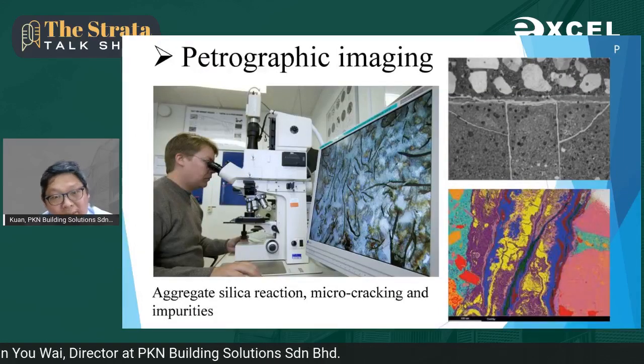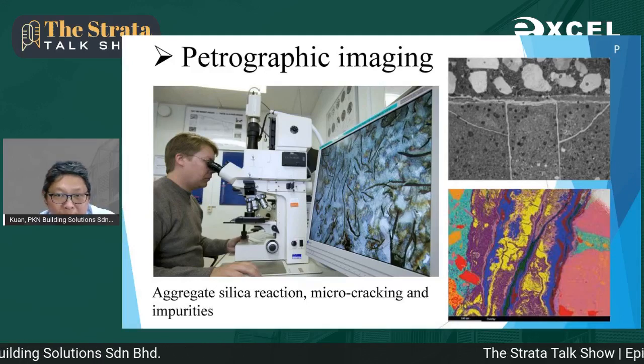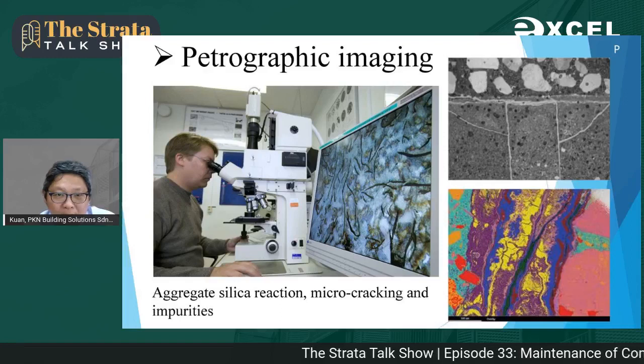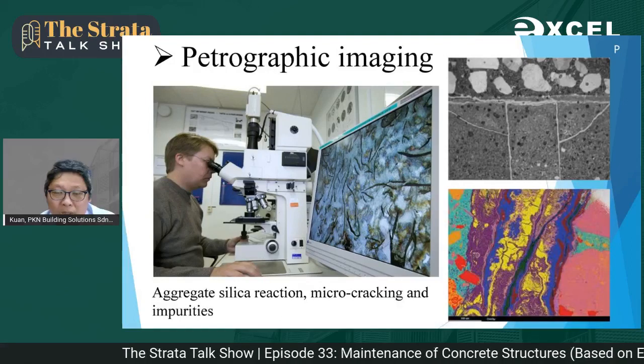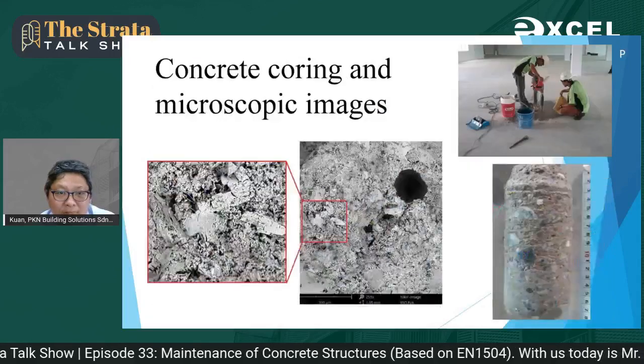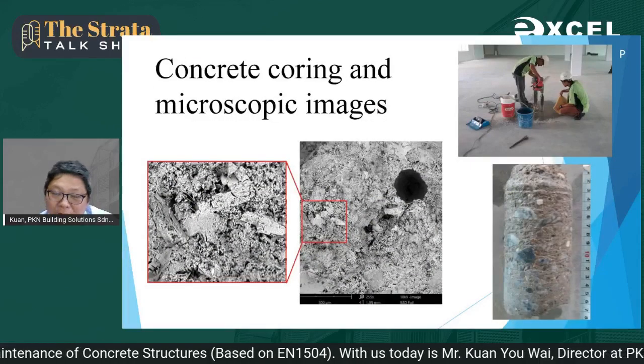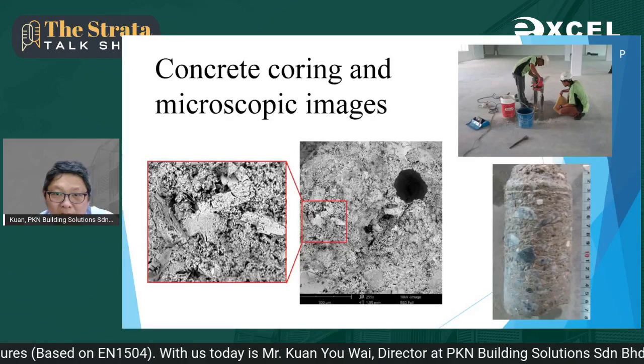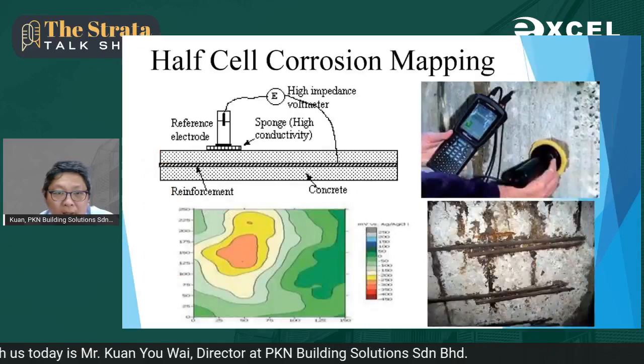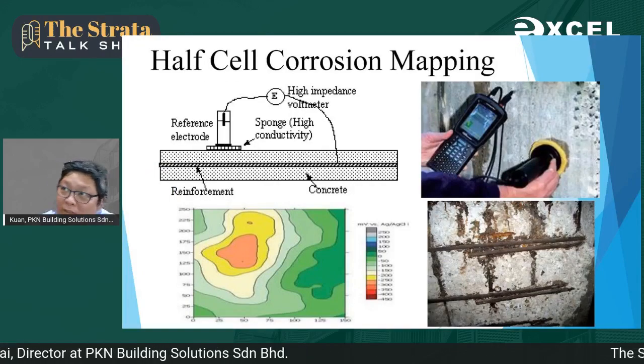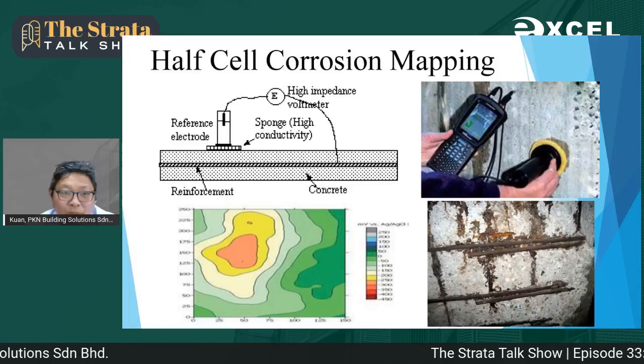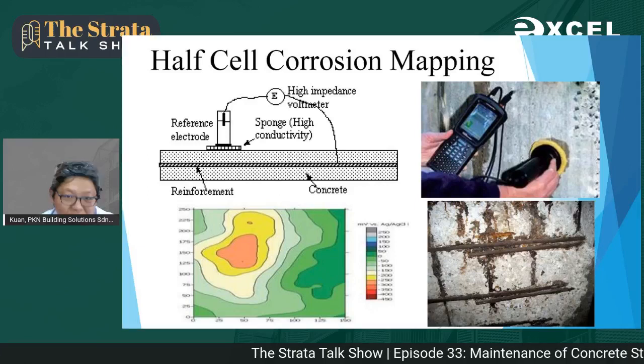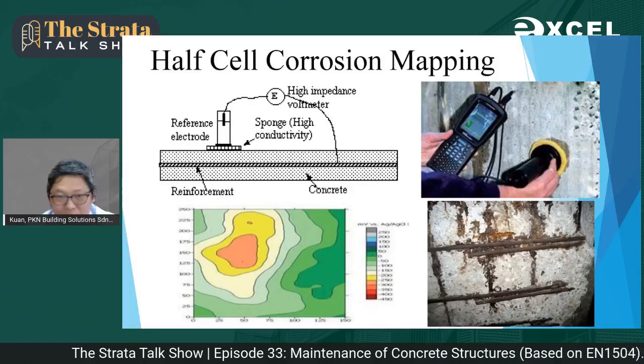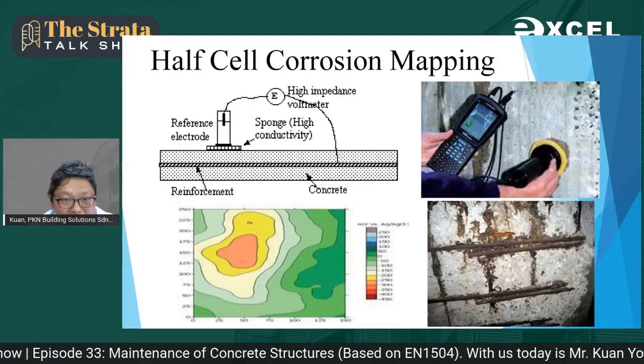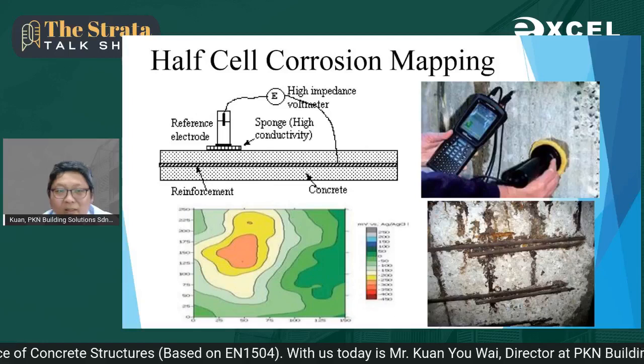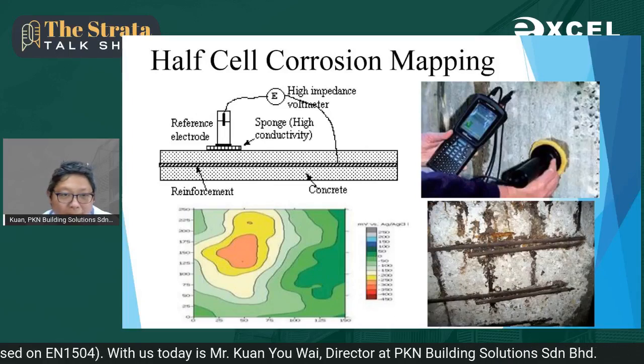And of course, we can take the specimen, take the core, and send it to the lab and use a high precision microscope to see what is happening inside the concrete, known as petrographic imaging. This is what we have done in one of the hospitals in Seremban. This is the actual work that we have done. And in terms of corrosion, because corrosion is an electrochemical process, we can use a voltmeter to measure the corrosion risk, based on this diagram. Then we can map out the different locations, which location has the highest risk, and see how bad the corrosion has become.